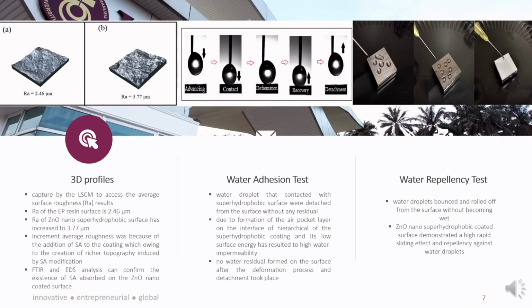Next are the 3D profiles of the coated samples, captured by LSCM to assess the average surface roughness of the EP and zinc oxide nano superhydrophobic coating. Ra of the EP resin surface is 2.46 micrometers, most likely due to the coarse structure produced on its surface. Ra of the zinc oxide nano superhydrophobic surface has increased to 3.77 micrometers. The increment in average roughness was because of the addition of stearic acid to the coating, owing to the creation of a richer topography induced by stearic acid modification.